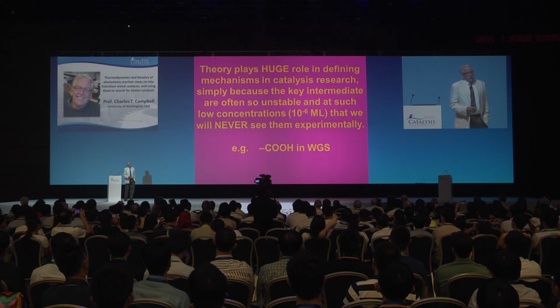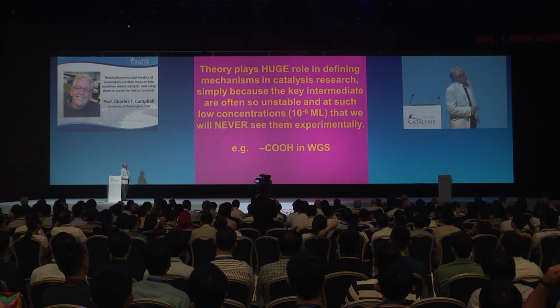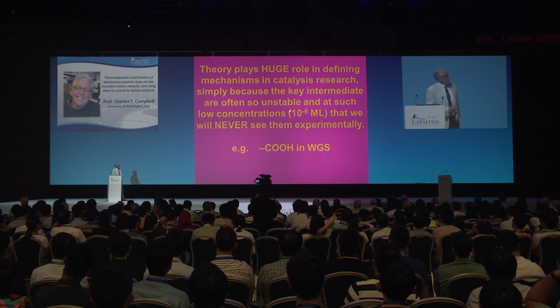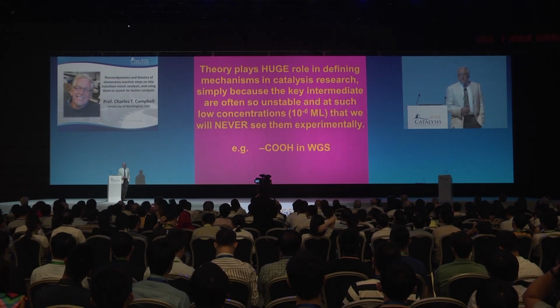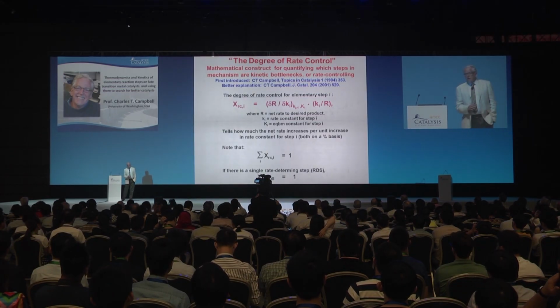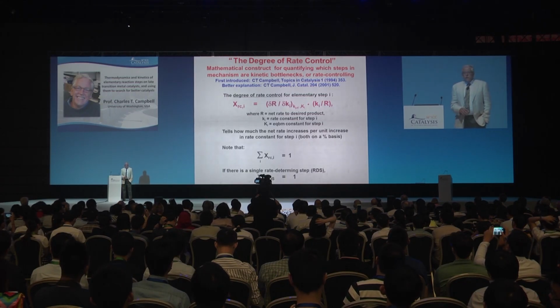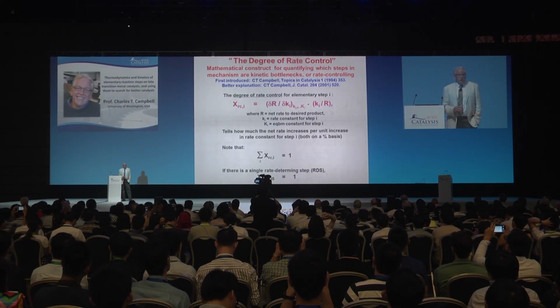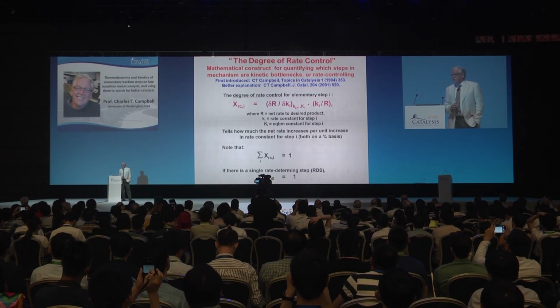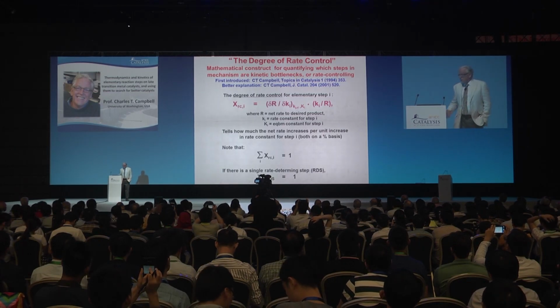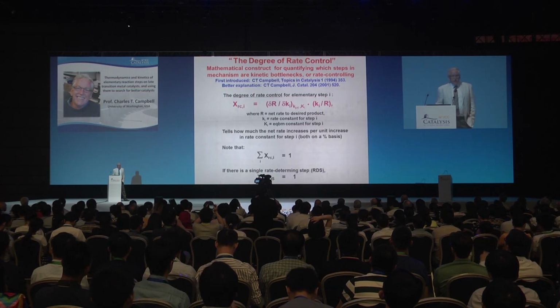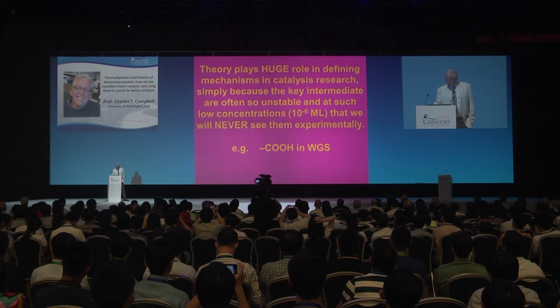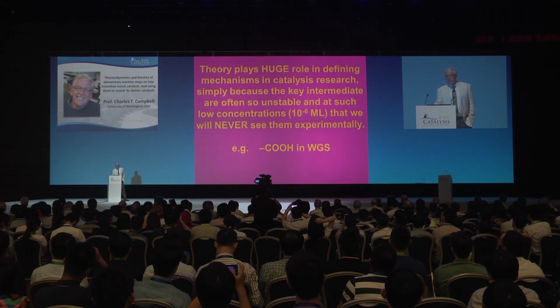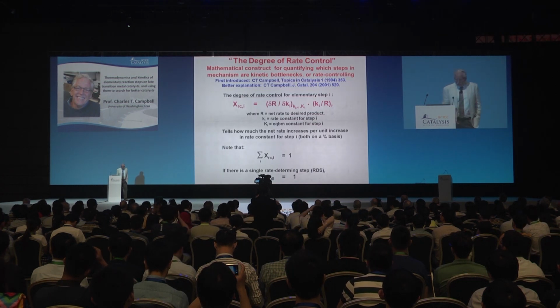And one area that's super critical is understanding what the mechanisms are and what are the key intermediates. It's very common that under steady state reaction conditions, a key intermediate has a coverage that's only 1/millionth of a monolayer. You just would never capture that really with any kind of experimental techniques. And so to know, for example, that this COOH intermediate exists, one would really have to rely on something like density functional theory to show that.